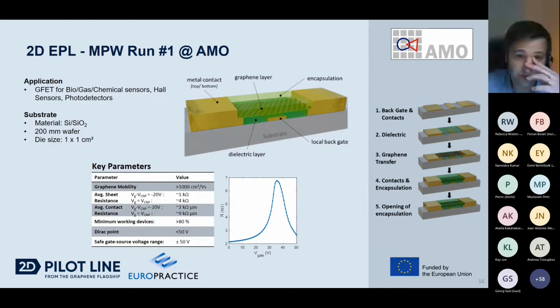So what we have chosen here is the following. We have a GFET with a top and bottom contact, with a graphene layer on top of a local backgate and with an encapsulation. The whole device is on a silicon oxide substrate, and we will fabricate this on a 200 millimeter wafer, which will then be diced into 1x1 sizes for the individual chips.